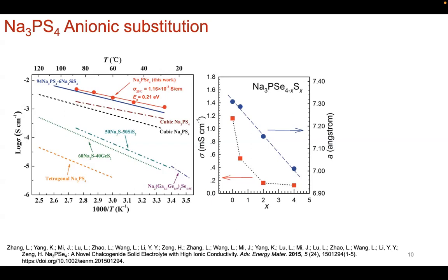Now we talked about also for lithium ion battery solid electrolytes, we talked about disorder and how site defects can increase ionic conductivity. We also talked about widening the bottleneck, the diffusion pathway. So similarly, this has been done for sodium ion solid electrolytes as well. In this example, what you'll see is substitution on the sulfide site with selenide. And what people have done is introduce disorder via substitution of the phosphorus with silicon. So you see here the glass ceramic. What you see is increased ion conductivity from Na3PS4 to that of the glass ceramic Na3PS4 mixed in with Na4SiS4.